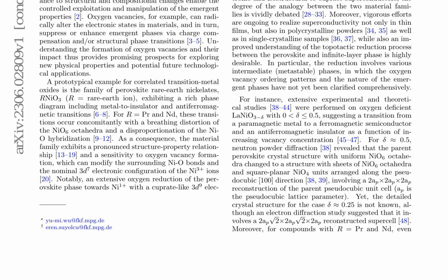To investigate the crystalline quality of a 20 micrometer piece broken off from a larger as-grown crystal, single crystal X-ray diffraction, XRD, was performed. The XRD data indicated a high crystalline quality and can be refined in the orthorhombic space group Pbnm, consistent with PrNiO3 single crystals and polycrystalline powders. The refined Ca content of the crystal was 8.6%, and the refined lattice parameters and atomic coordinates are presented in